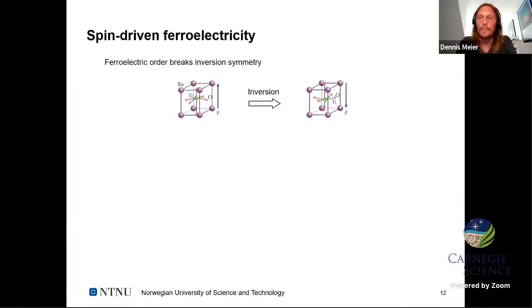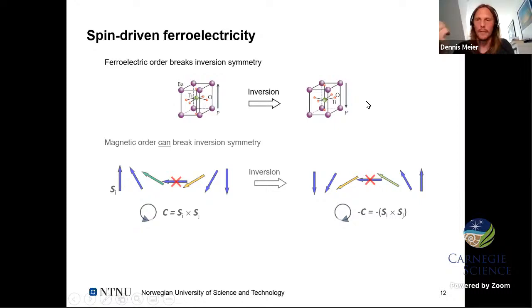Let's start with the spin-driven. I just said that in our standard systems like BTO, it's a displacement inversion symmetry breaking that causes the ferroelectric order. So by this displacement, inversion symmetry is broken and we end up with a plus P or the minus P state. In a spin-driven system, we can also have inversion symmetry breaking caused by the magnetic order if the spins order in specific ways. And what you see here is one of the spin structures that can give ferroelectricity, or first break inversion symmetry and thereby kind of prepare the stage for ferroelectricity.